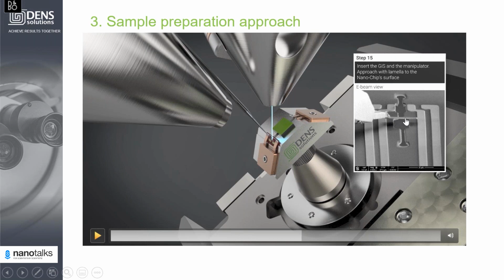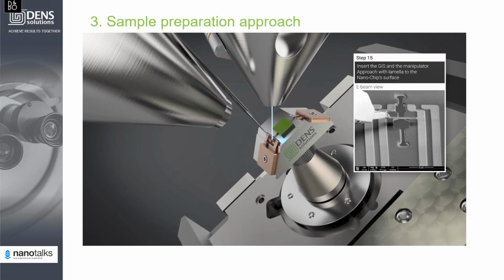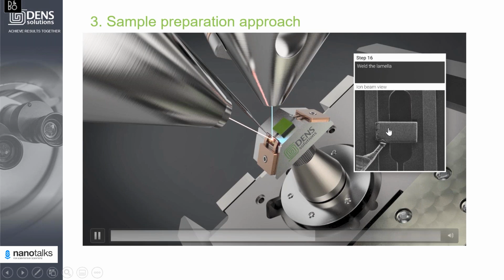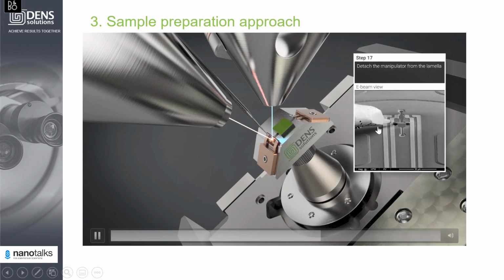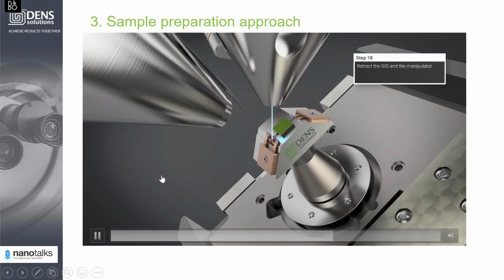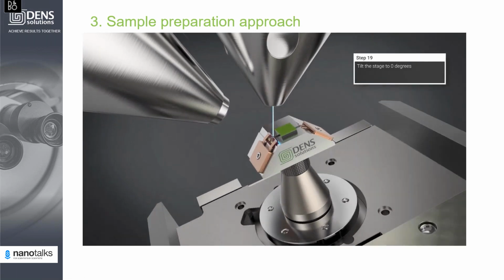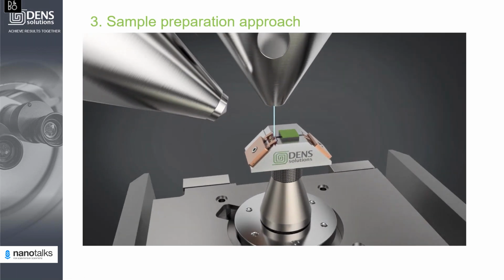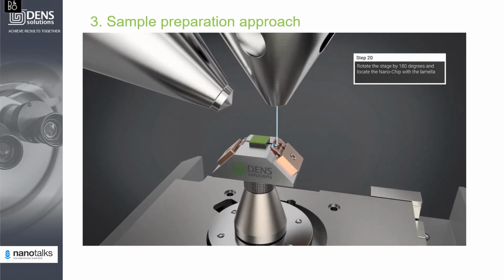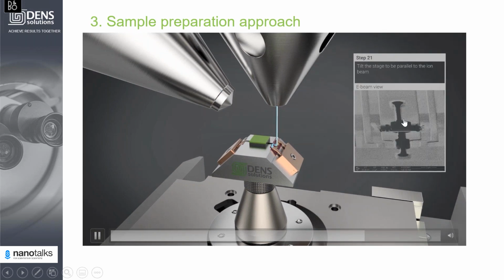And as you can see, we don't put the lamella parallel to the Nano-Chip. We put it at a slight angle of 9 to 10 degrees. And the reason for that is to be able to mill the lamella from both sides. So when you have the lamella next to the surface, you make a weld, you release the manipulator, you take out the GIS and the manipulator, tilt the stage back to 0 degrees, rotate it. So here you see our sample area with lamella.